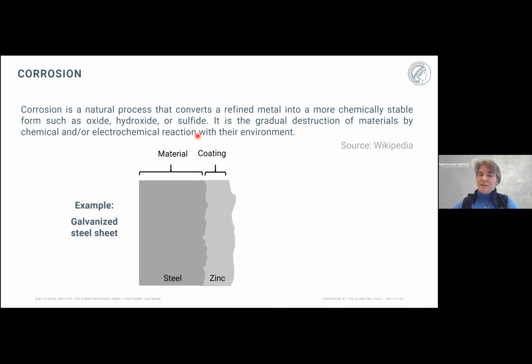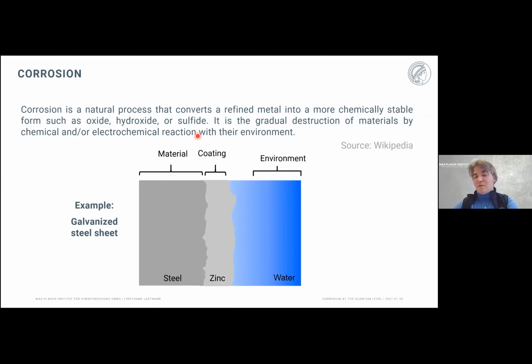But of course, this is still a metal, and a metal in an oxidizing environment is not in a thermodynamic ground state. The thermodynamic ground state would be some kind of oxidized form. So when the metal comes into contact with water, for example, then some kind of oxide, hydroxide, sulfide, or some oxidizing layer would form. And it would be nice if this layer is really protective, and there are oxide layers that are protective and really prevent further corrosion of the material, but this is not always the case.